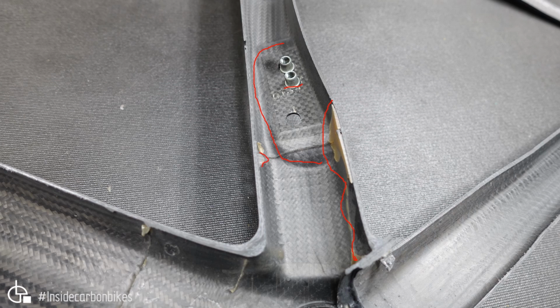For example, if there's a void in the wax mandrel when they cast that mandrel, then resin can fill that space as well. So you can get a little bit of resin buildup like that, but as I said before, it's very difficult to get voids if all the pressures are correct.